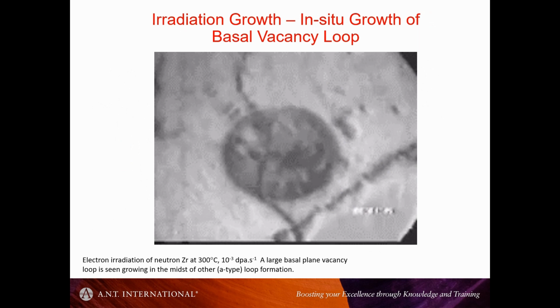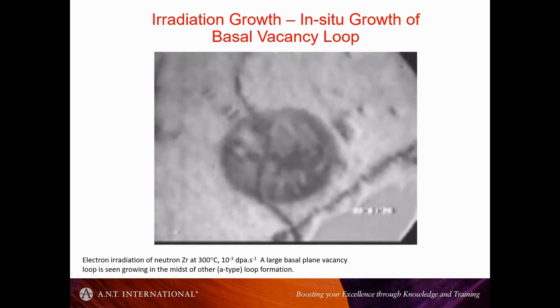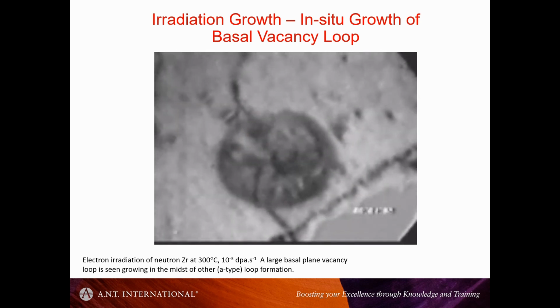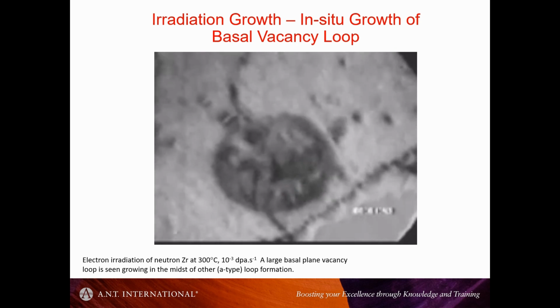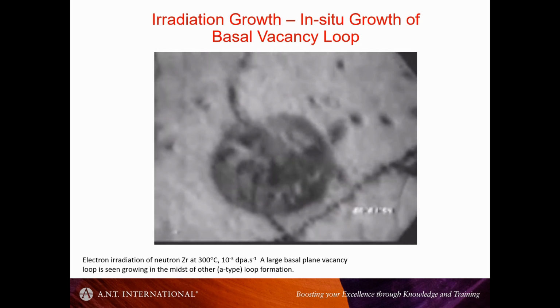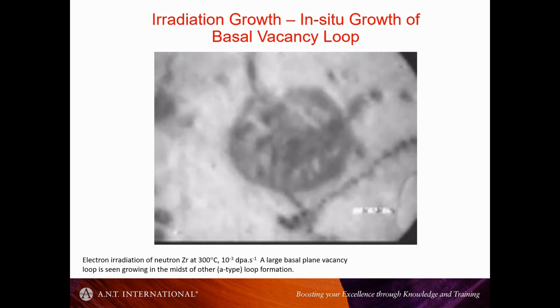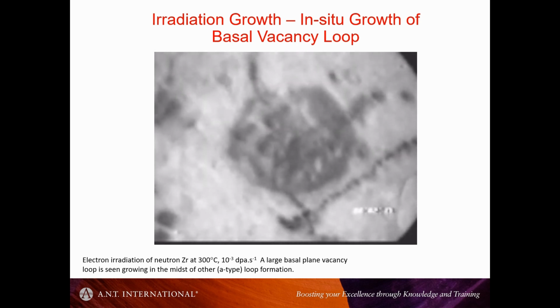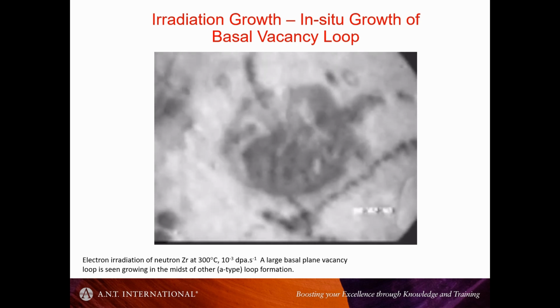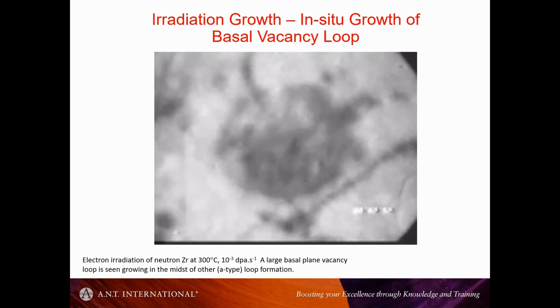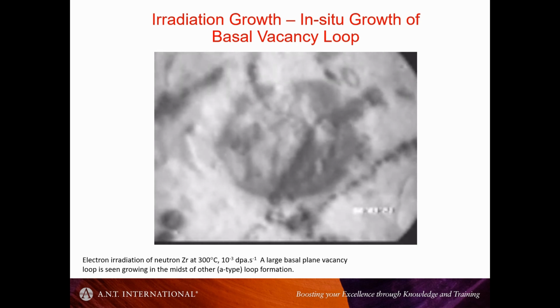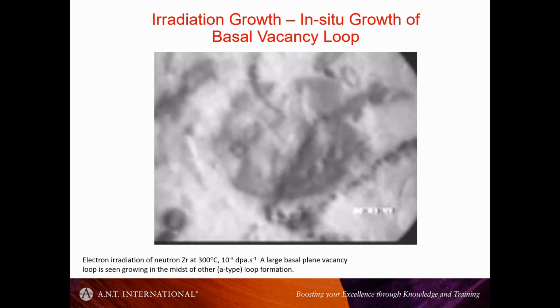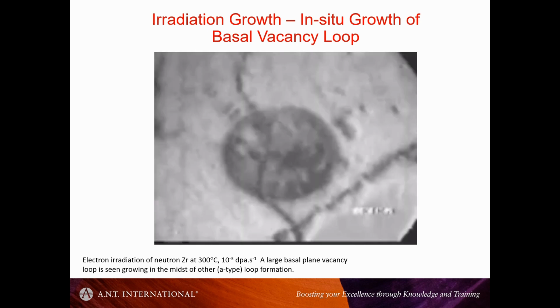I'm just throwing this in to illustrate a little video I took when I was a student doing my PhD, of a C component loop in zirconium in the high voltage electron microscope. So we're using the electrons to image the material and at the same time damaging the material, creating point defects at an elevated temperature, 300 degrees C in this particular case. And you can see how the loop is growing and how other defects are produced.